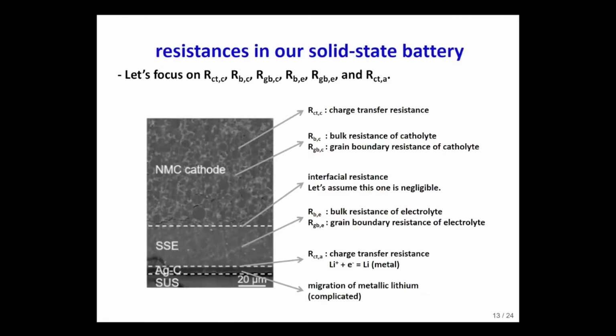Then, which interface is responsible? There are many resistance components in our solid-state battery. If you look at the cathode, there is charge transfer resistance on the surface of the cathode active material, and bulk and grain boundary resistances for the solid electrolyte.